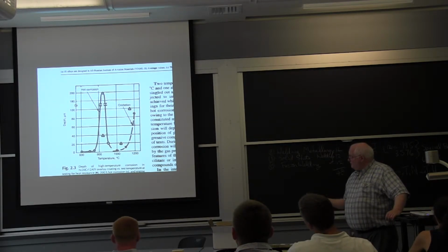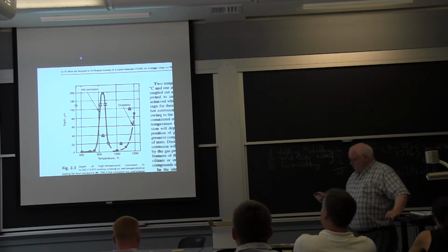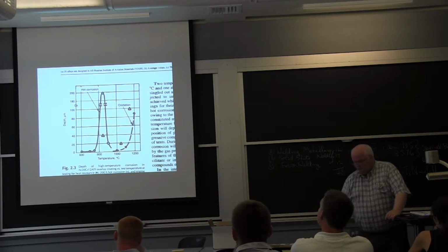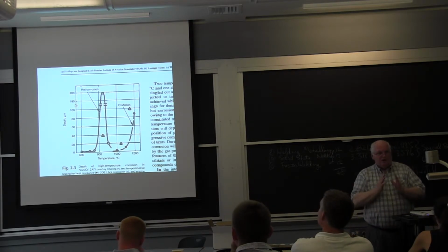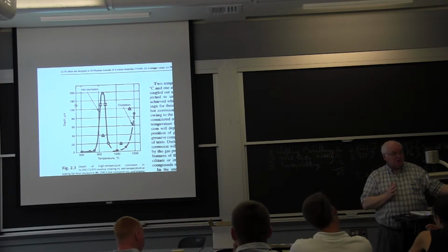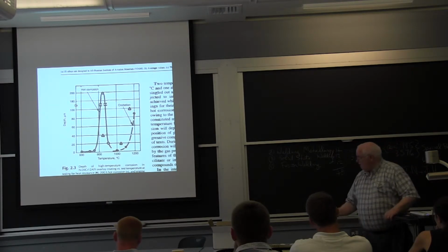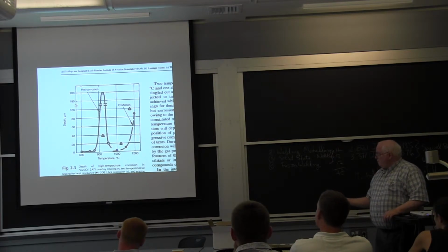And notice here, this goes from 0 to 100 and then up to 200. So really this peak is about twice as tall, okay? You have a huge increase, about a factor of 200 increase in the corrosion rate over a very narrow range, where kinetics are too slow for the diffusion at low temperatures, and all your gaseous products are vaporizing away, they're not condensing. There's this one condensing region. Now, this is the type of corrosion that occurred on those turbine blades.